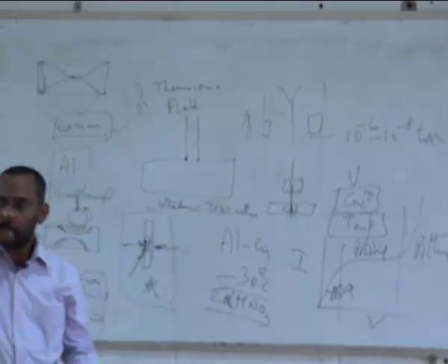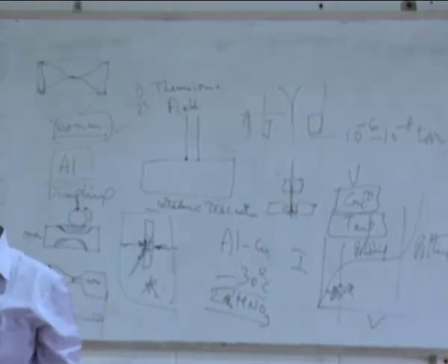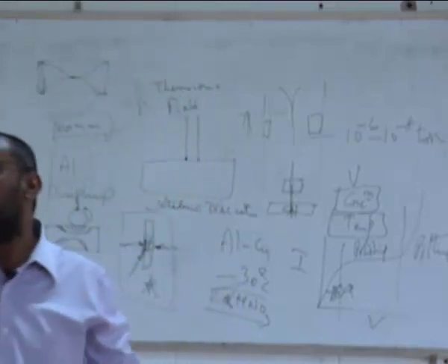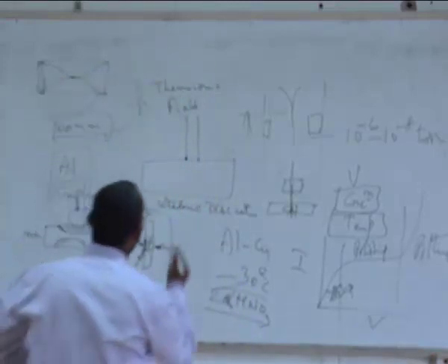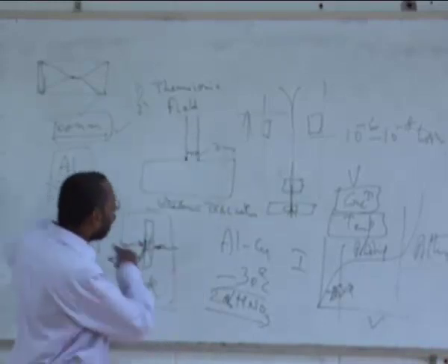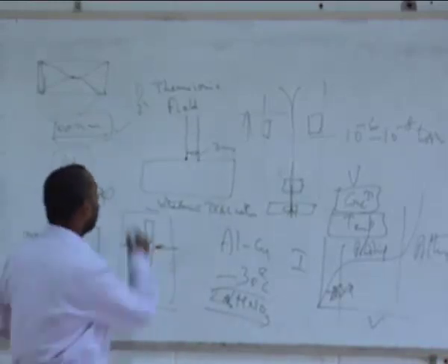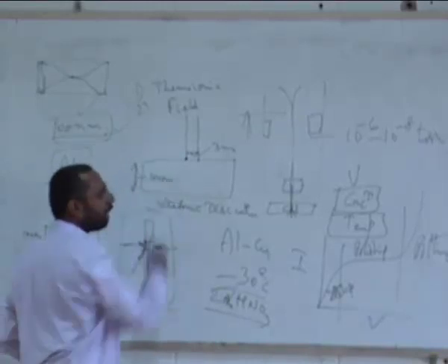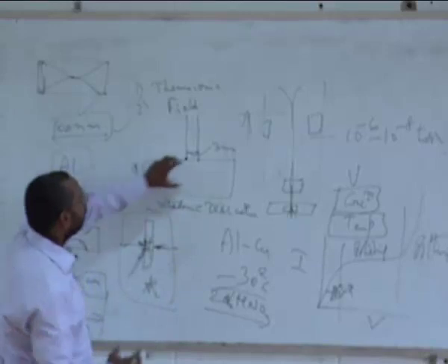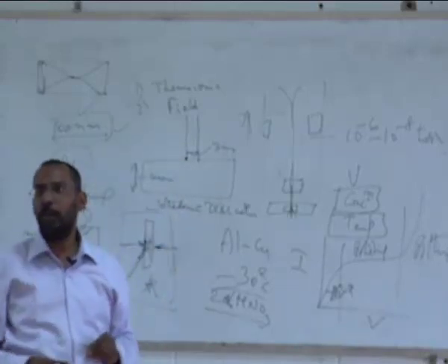By ultrasonic vibrations, it penetrates through the sample and keeps on rotating so that it scoops out a 3 millimeter disc out of it, because the diameter here is 3 millimeters. And already I have sliced my sample and maintained this thickness as 100 microns. So now I have a sample which is a 3 millimeter round pellet with a thickness of 100 microns. Then I start from there and do dimpling and then ion milling, and finally the sample is ready.